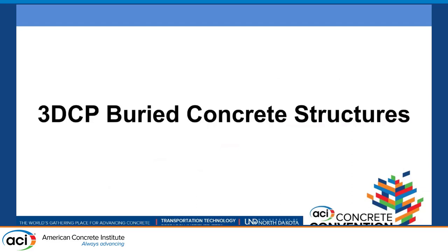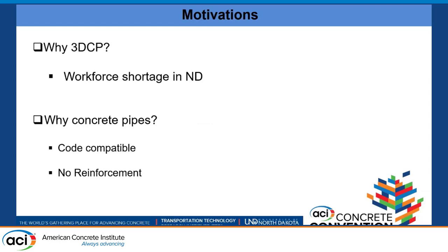We conducted a 3D CP buried concrete structure study. The main reason was that workforce shortage is a big issue in North Dakota, which is why the University of North Dakota adapted this technology. We decided to print concrete pipes to produce code-compliant structures, compare them to code requirements, and evaluate their structural performance relative to conventionally made concrete. We chose not to use reinforcement because studies show that reinforcement can affect the structural performance of 3D printed walls due to introducing voids.